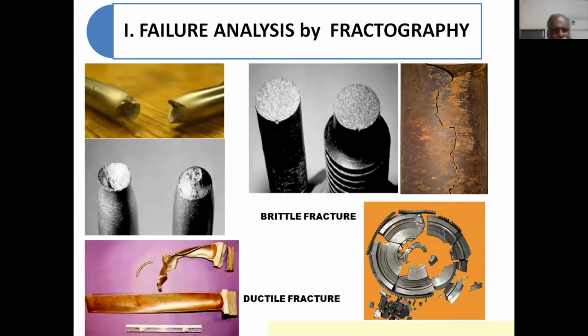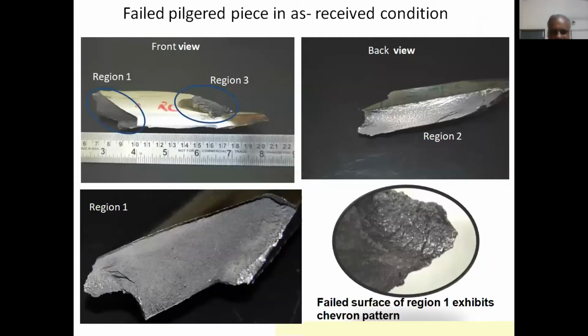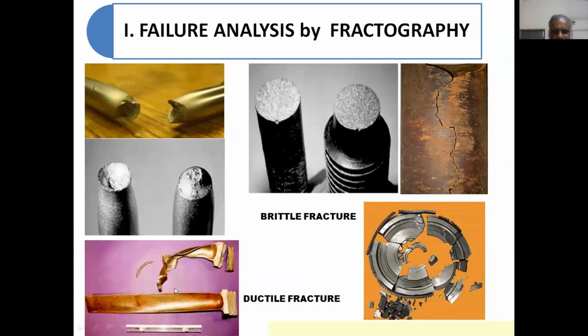Okay. And in the case of ductile failure, why is it so important? Any example? For example, a turbine blade: if it extends a little, even by a fraction of an inch, it is sufficient that it will touch the surface of the dome. Therefore, ductility matters: if the material gets elongated, there is a limit to the service. So turbine blades are designed for 1% strain or something like that. So this is how you should have certain important properties, for example, in this case, ductility for the turbine blade. Okay, you have to specify.